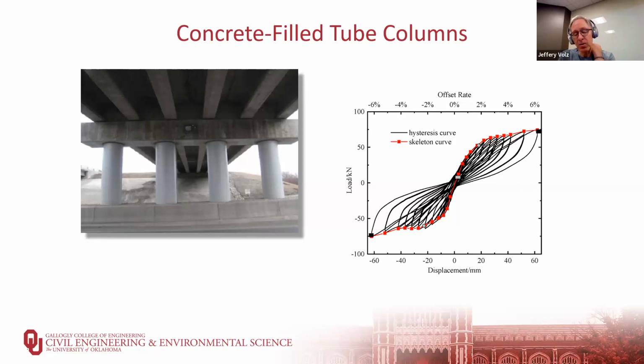It'll start to corrode. And our piers, our bridge piers, the columns, if you have an overpass, are right in the splash zone, where that's actually the worst you can have, where you have that constant wetting, drying, wetting, drying with chlorides will cause it to corrode. So that's one of the downsides. But still, it performs very well in terms of its ability to absorb energy.